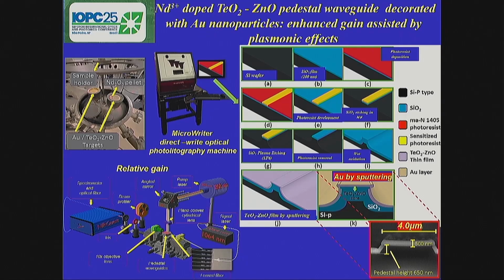In this figure, I show you the final profile of our waveguide with 800 nanometers for the core, and 650 nanometers for the pedestal height, made of silicon dioxide. In this figure, I show you a waveguide with 4 micrometers width, but we produce different widths, as I'm going to show you. The relative gain is measured using this setup in which the pump is at about 800 nanometers. The signal operates at 1 micrometer. It's sent to the sample and coupled to it by a lensed fiber with 2 micrometers diameter. And then at the output side it is sent to a spectrometer by an infrared fiber. The signal is collected to be then analyzed.